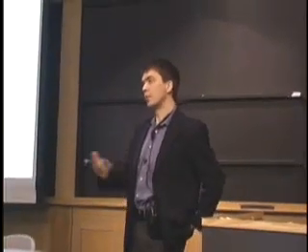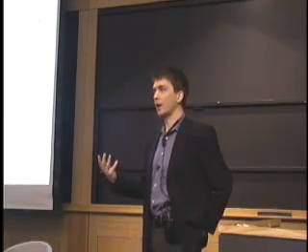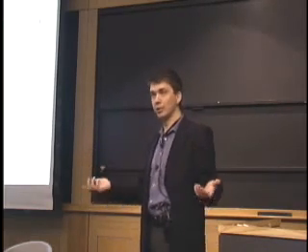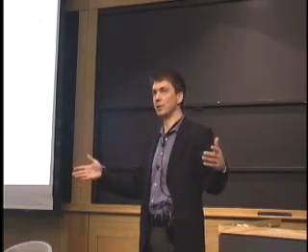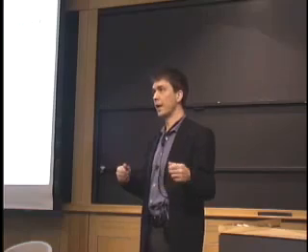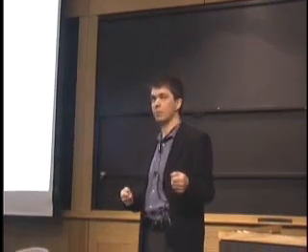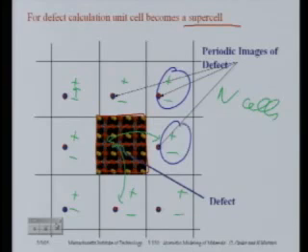Okay? And if you're smart about it, so the brute force way to converge supercell calculation is always to push them as hard as you can and hope and sort of see the energy converge of the defect. But if you're smart about it, you can often do much smaller cell calculations and explicitly take out the term that's the defect-defect interaction. Okay? Which is, if you know that this is a dipole, you know what the form is of it, and you can take it out. Okay?